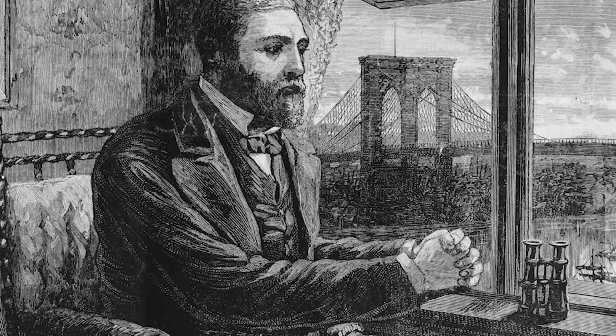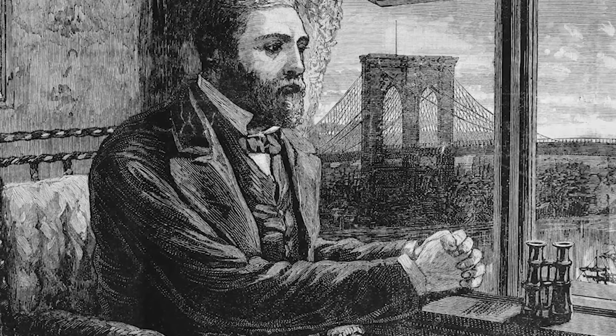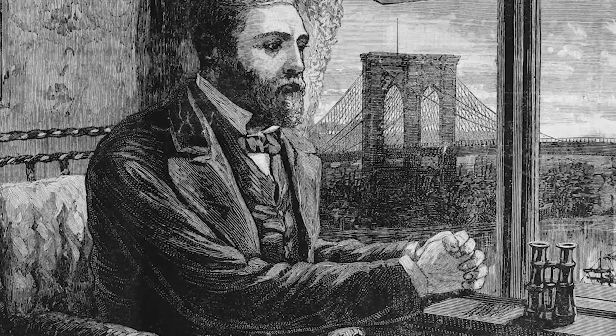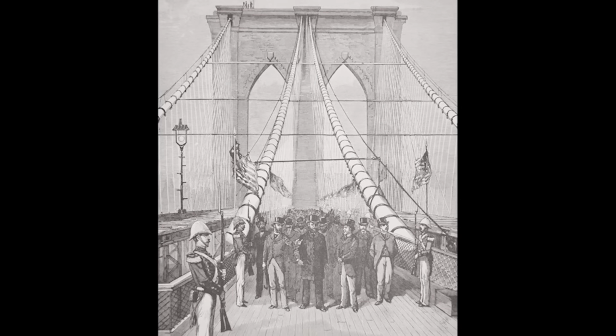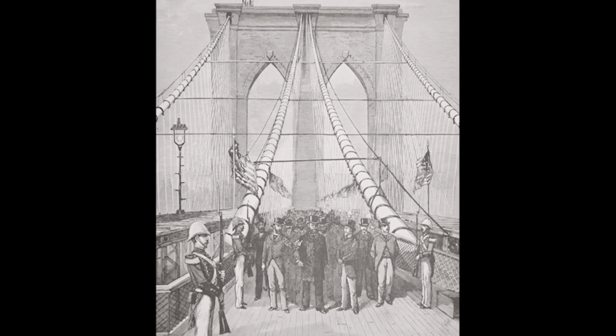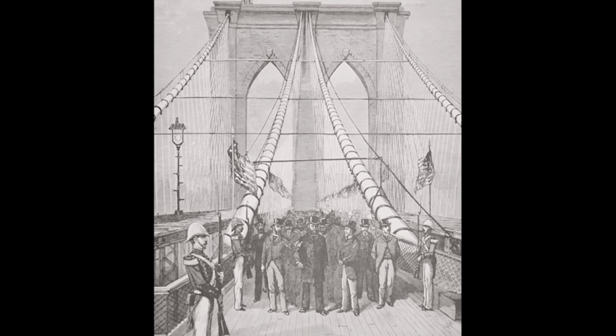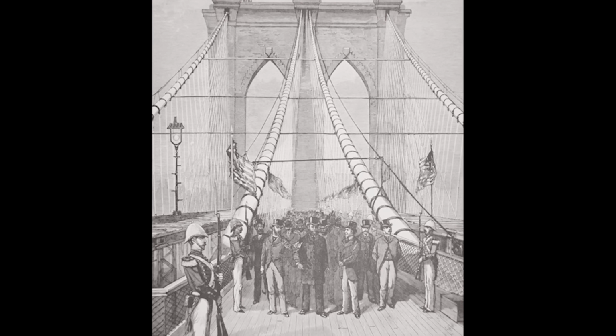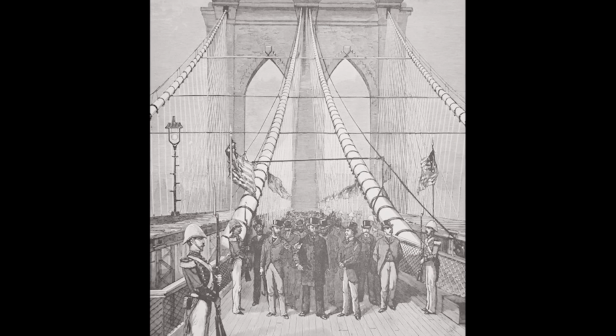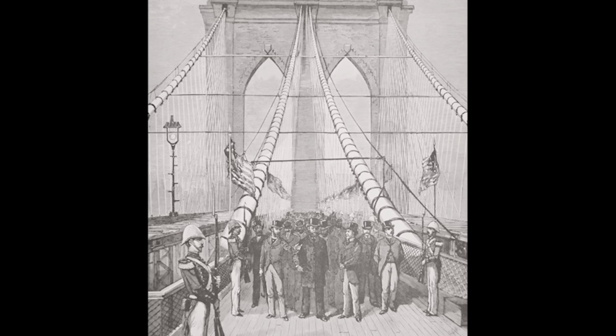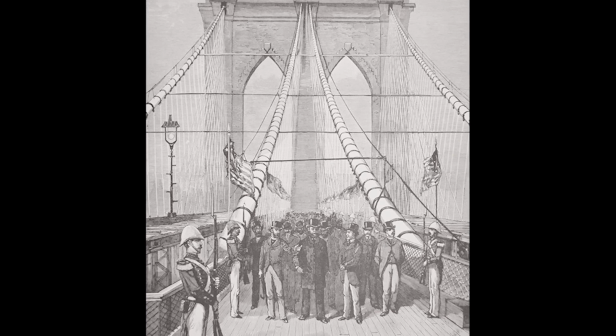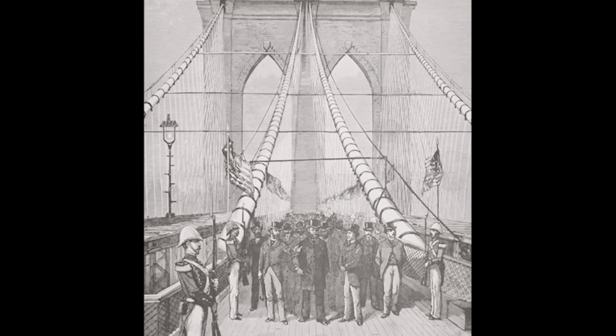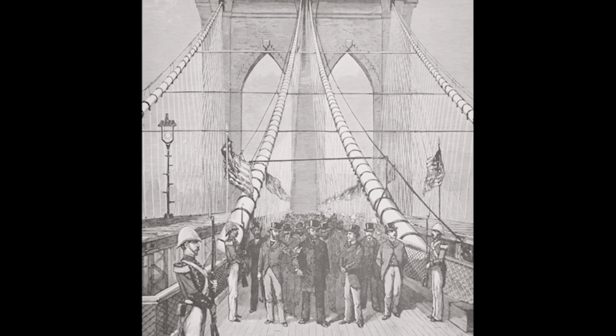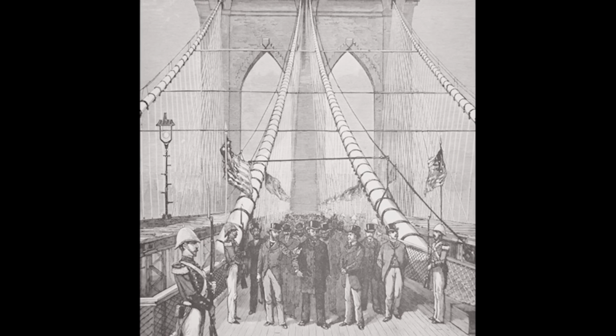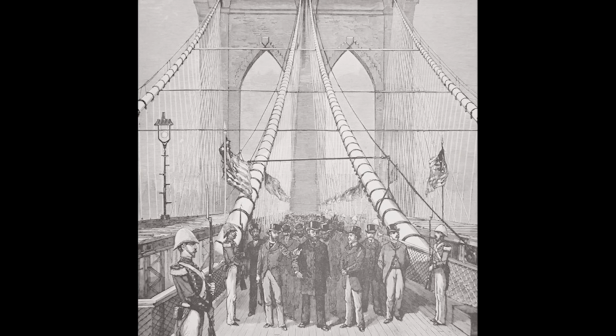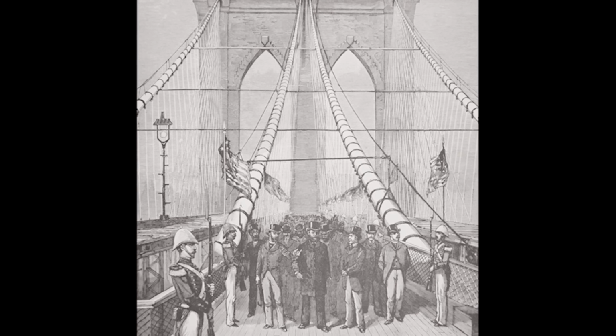Modern cable systems demonstrated the consequences of different protective philosophies. Thin galvanized coatings measuring 25 micrometers could experience 50% zinc loss within 20 to 25 years when protective seals failed and moisture reached the coated surfaces. Contemporary wrapping wire often carried Class A galvanizing at approximately 0.6 of an ounce per square foot, roughly 1 mil thick, compared to the multi-ounce coatings and thicker barriers that 1870s specifications had required.